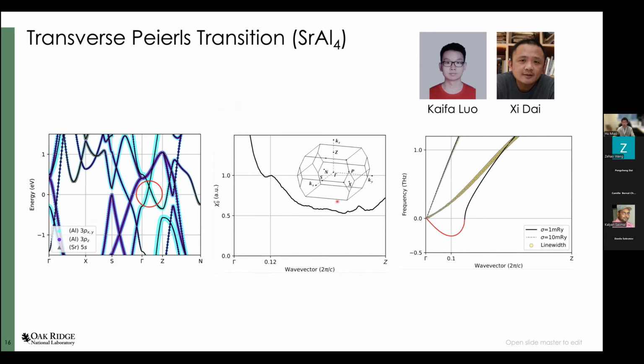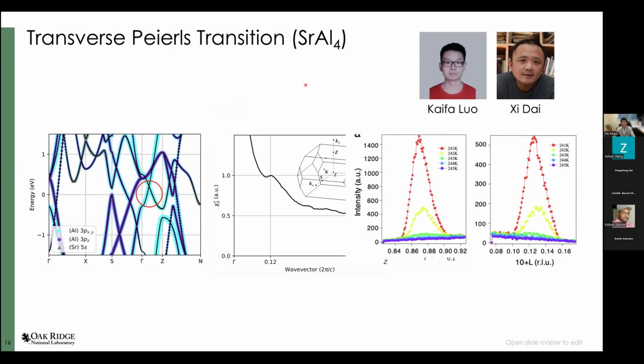We can also calculate the electron-phonon coupling and the phonon dispersion at finite temperature and zero temperature. Again, you find the phonon softening induced by transverse electron-phonon interaction. I have to mention that this calculation was done for strontium aluminum 4, because europium is sort of a heavy f-electron element, and to properly treat it may have a problem. But we also performed a measurement for strontium aluminum 4, and we confirmed the CDW is exactly at the DFT calculated wave vector.